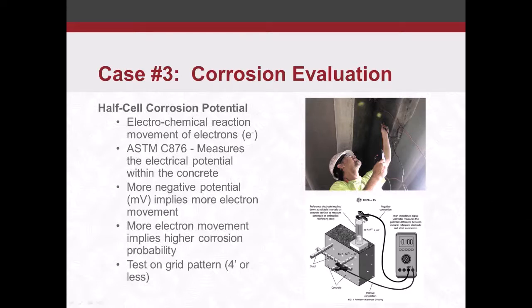So what we do, this is an image also out of ASTM C876. We have to physically connect one electrode to the reinforcement, and then we've got another electrode that's got a copper sulfate solution that has a known, very repeatable voltage potential. Then we put that electrode on the surface and measure the electrical potential of the concrete surface itself. You can see here in this digital voltmeter, it's got an electrical potential of negative 100 millivolts. And the more negative, again, the more likely there is corrosion.